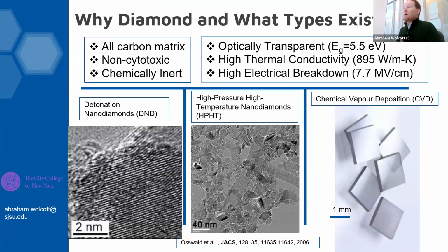So when we think about diamond, not all diamonds are the same, and I think that's an important aspect. On the left-hand side, we have detonation diamond, which is a lower quality material. It doesn't host NVs as well. On the right-hand side, you have chemical vapor deposition diamond, which is of higher quality and it's more expensive. Now, for each one of these materials, of course, they have an all-carbon matrix. They should be non-cytotoxic and be chemically inert. And we know about their optical transparency, the high thermal conductivity, and high electrical breakdown.